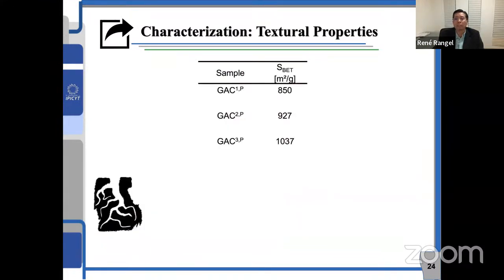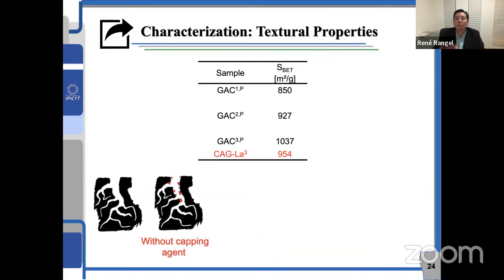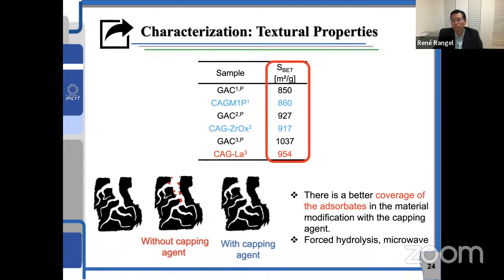One of the challenges is not to block the porosity of the activated carbon. Here, as an example, I show three materials with different surface area. Once we anchor lanthanum, for example, the surface area decreases. But if we use a capping agent, we manage to keep the surface area, and in some cases it even increases a little bit. We have a better dispersion. And in this case, the metal oxide is not just impregnated on the surface, it is actually anchored on the surface. Again, this is very, very important.